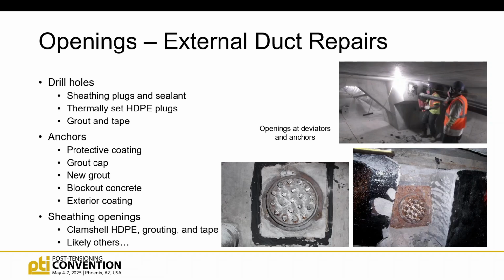At anchors, which are on the bottom here, once they get it opened up, often they'll apply a corrosion inhibitive coating. They'll get a grout cap. Sometimes that's a bit of a challenge because they didn't have a grout cap, so you have to figure out how you're going to install the new grout cap onto the old anchor plate. You'll re-grout those. We'll put the concrete block-out back, and then put coating back over the top.